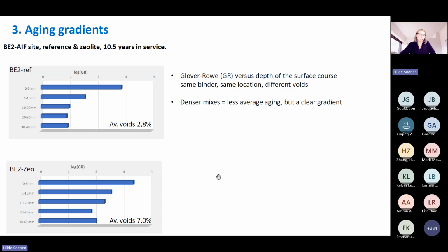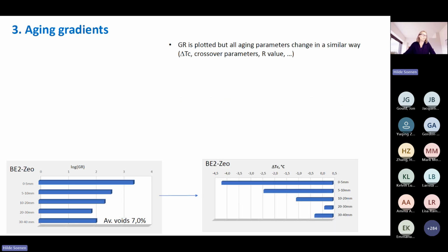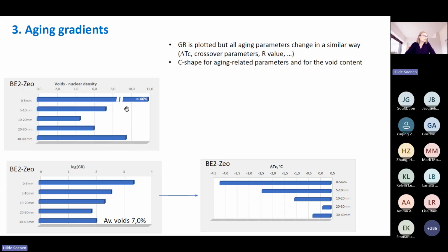Now I showed you log Glover-Rowe, but I can as well show you the delta TC level. So you see it shows the same shape as the Glover-Rowe parameter. And in this case, and we observed that very often, we saw a C shape in the properties versus pavement depth. And if we then looked at the nuclear density, even there we saw a C shape. So probably this is related to each other.